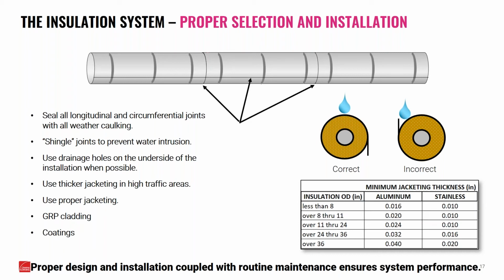Another recommendation would be to use drainage holes in the underside of insulation when possible. And again, this is only for a hot system. You do not want to do that for a cold system. But if you do have an area that could potentially accumulate moisture, that's certainly a consideration. We talked about this earlier, but using thicker jacketing in high traffic areas certainly makes sense, and it's a lot cheaper than having to replace insulation or having to go back and remediate a section that's been affected by CUI because the jacketing has been damaged.